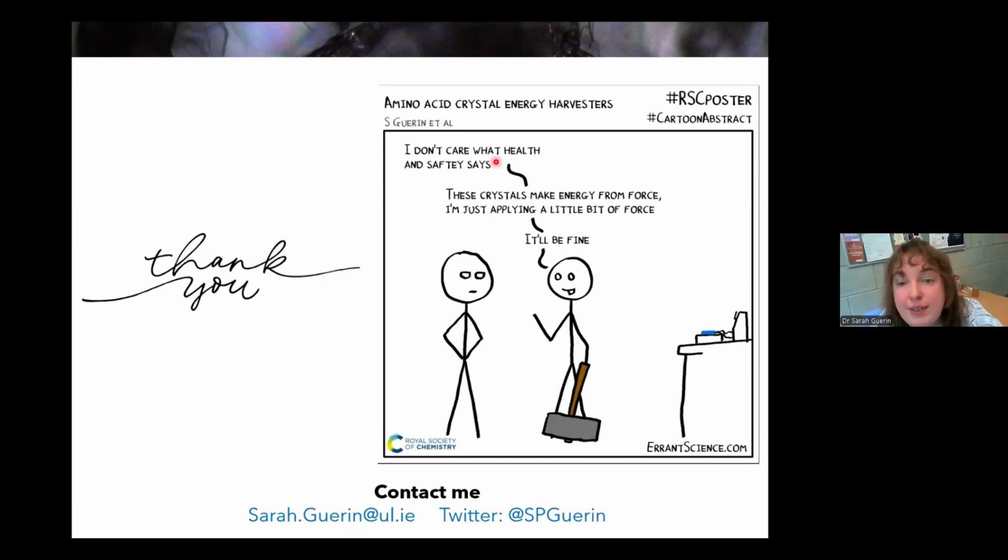In terms of techniques, Tara Ryan in my group, her whole PhD is these polymer coatings. Because we're trying to coat those discs and plates you saw, we need three-dimensional uniform coating. So for us, dip coating seems to be the most successful, where you're submerging your crystal component into your solution and then removing it very, very slowly at a particular rate, and then you're rotating it and covering it again in that same bath. Spin coating is very difficult to get uniformly around our entire device. It is challenging for us, so dip coating is what we found has been best.